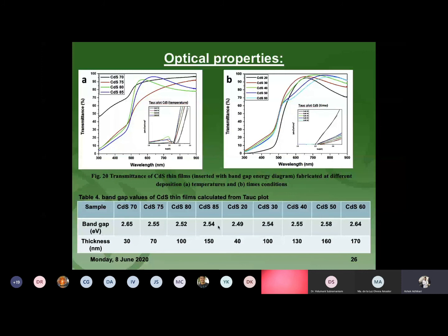We calculated the bandgap of the film by extrapolating the straight line between alpha h-nu squared versus energy in the plot, and observed that the bandgap is close to 2.58, meaning the film is stable with a hexagonal structure.